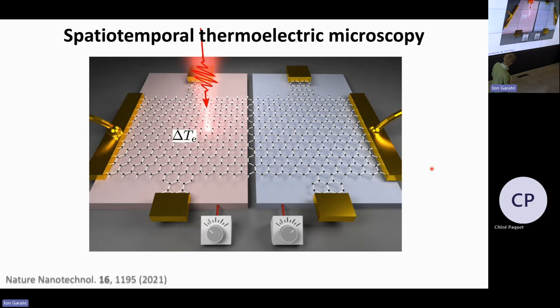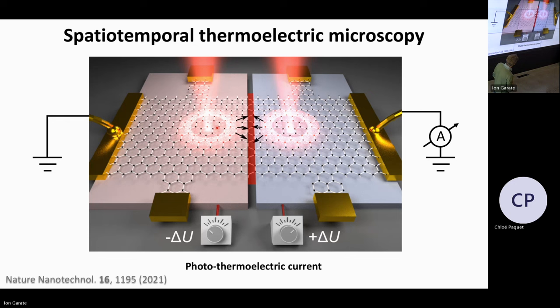So what we're going to do now is shine, again, an ultrafast laser pulse, which is going to create an electron temperature in the graphene channel, which is going to start spreading out. Then we're going to do the same thing on the other side of the junction with a second pulse, which is going to be absorbed, change the electron temperature, and then start diffusing out. Then at some point, both of these diffusing electronic heat blobs will meet at the interface where they generate a photovoltage. If you shine light just here in the center of the system, you don't generate any photovoltage because it's all symmetric, right? But at this junction, there's symmetry breaking, so you can generate a net current.